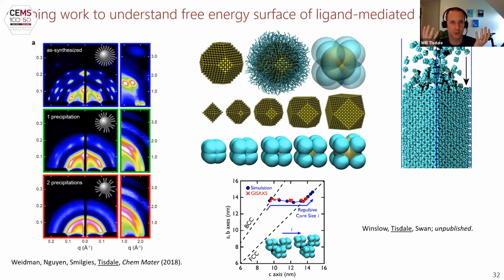This is an age-old question in colloidal assembly: what is the lowest energy structure? There's been a lot of work in gold nanocrystals that are much more isotropic and spherical in shape, showing a strong dependence on whether you get a body-centered cubic or a face-centered cubic structure, depending on the ratio of the ligand length to the diameter. There's also theoretical work that Kamien and Ziherl did in soft corona hardcore micelles, where depending on how soft the outer sphere of your colloidal particle is, that determines the lowest energy structure, whether it's FCC or BCC or even some Frank-Kasper phases that can be predicted.